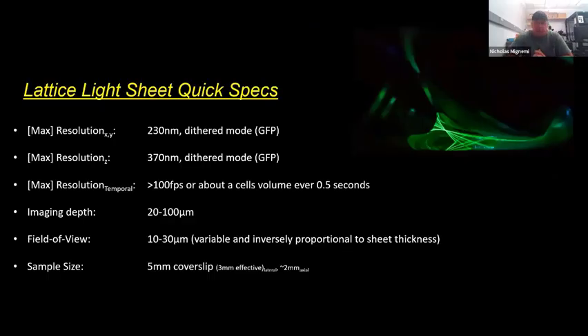So let's talk about some quick specs on the lattice, right? The lattice has a max resolution in the dithered mode, and that's where we move the sheet across. This isn't lattice SIM. It's about 230 nanometers. It has about a 370 nanometer resolution in Z. We can get a cell volume, roughly.